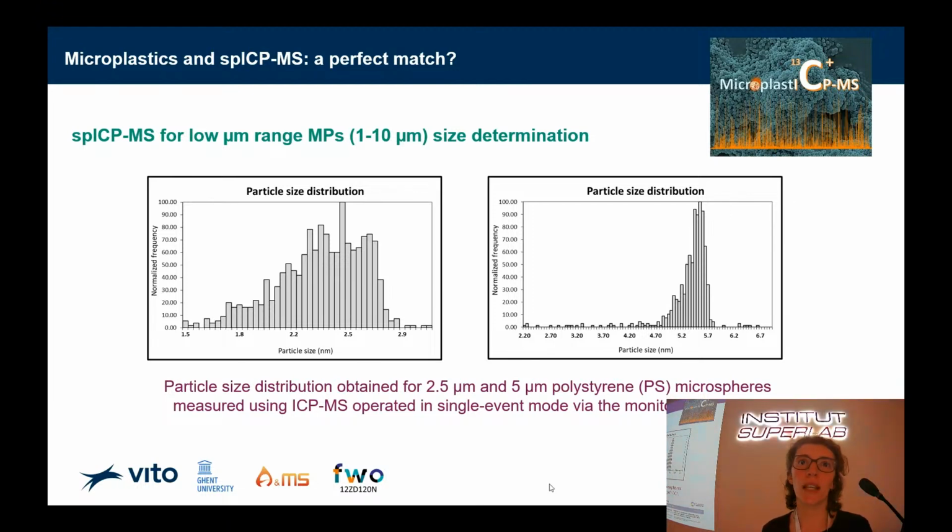For those who don't know what single particle ICP-MS is, most of you were maybe today also at the PerkinElmer presentation on ICP-MS. So basically, we were using the carbon isotope to obtain the particle size distribution of microplastics. In this case, you can see the particle size distribution obtained by monitoring carbon-13 by ICP-MS in the single event mode,